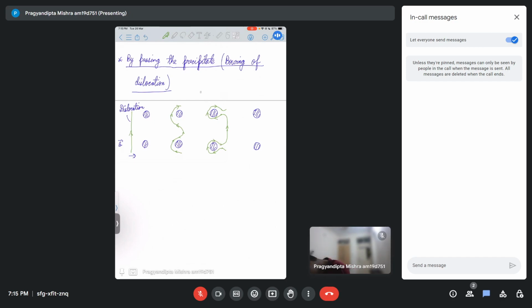So you'll see that if you see this region, right, the dislocations are of opposite signs, right? And same thing would be here also. They are of opposite signs. So because they are of opposite signs, they will annihilate each other. Okay, they'll just mix. And then they leave behind something around the precipitate, and then the dislocation comes out separately. Okay, the same Burgers vector. It leaves behind a loop around the precipitate and just comes out.